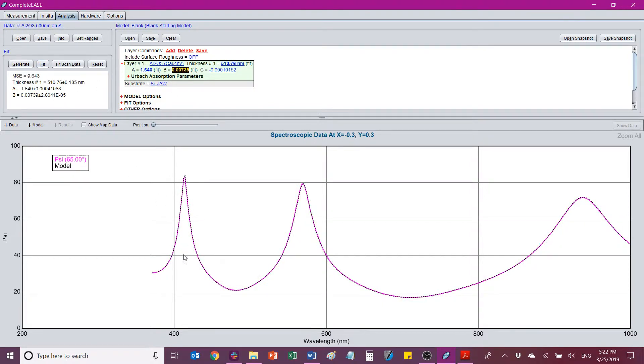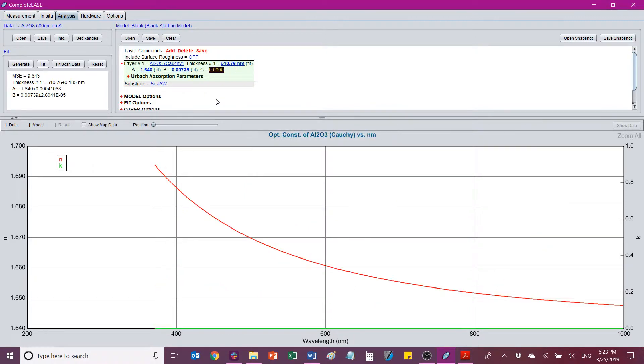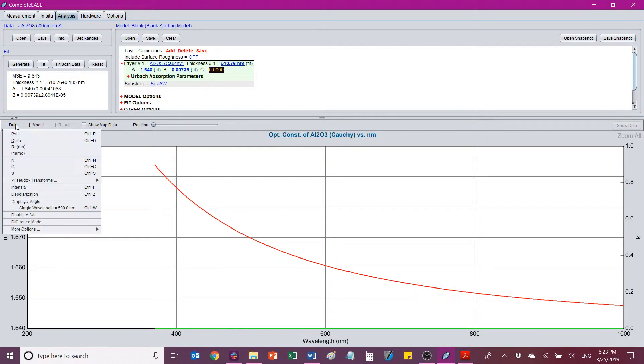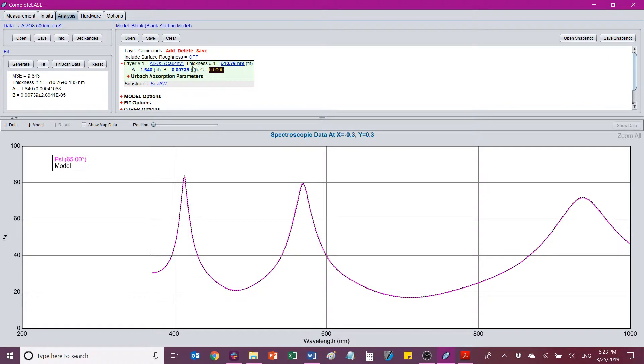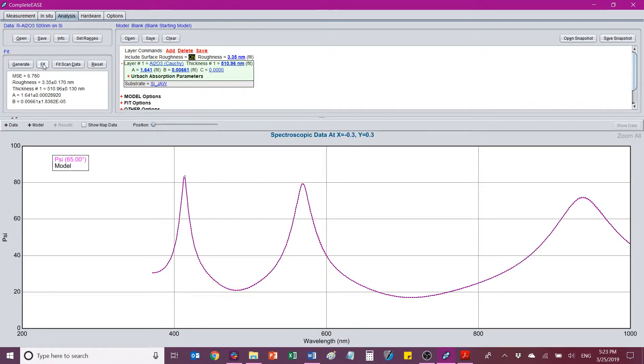Now, this is really small. I could probably just make this zero and not fit it. Oh, this pops up. This is the N and K. Anytime you alter these, sometimes these will pop up. We'll just go back to data and just fit these parameters. Okay, that's a pretty decent fit. Though I may be able to get a better fit by incorporating roughness. So I'll just add fit for roughness and see if that increases it. It does improve it a little bit.